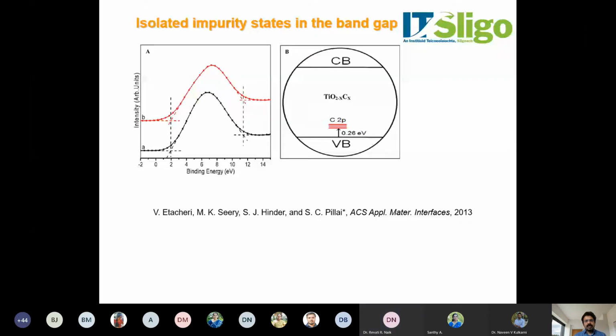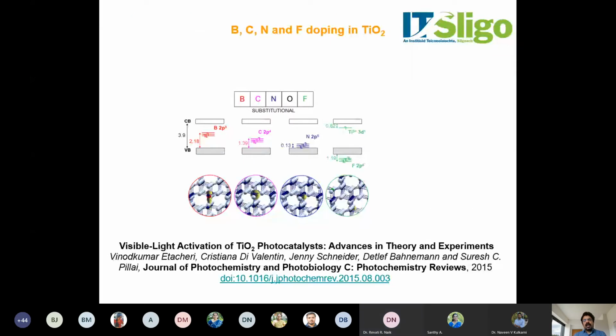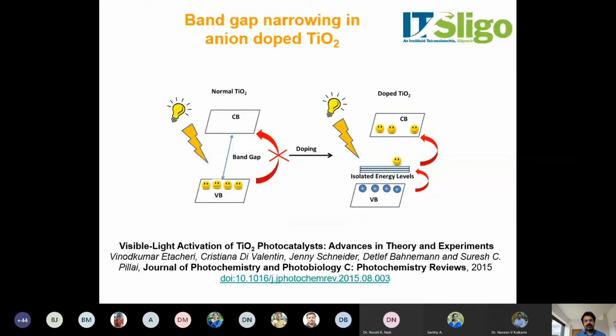So this is an example of carbon-doped TiO2. So we have developed a range of different types of dopants to make an additional energy level in between the valence band and the conduction band. Okay, so which means that you should be able to use visible light rather than ultraviolet light for this type of application, or make the TiO2 active in the visible region. So after doping, isolated energy levels are formed. This is an article written by Vinod and published in the Journal of Photochemistry and Photobiology, and this is also available to download. So you can get information on band gap narrowing in anion-doped TiO2, and also the theoretical and experimental development of visible light active TiO2 photocatalysis.